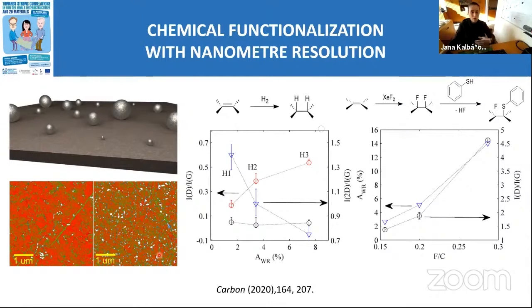If you have a more corrugated state, it means that you have more graphene which is bent. So the p orbitals are labilized. It means they will be much more prone to undergo chemical reactions, so uncover the chemical species on the wrinkle. So this was really a nice confirmation that if we just enhance the reactivity locally by local bending of the graphene, we can much more easily introduce the chemical functional groups only at the position where the graphene is strained. So this is a kind of general picture, and the last slide I would like to share with you.